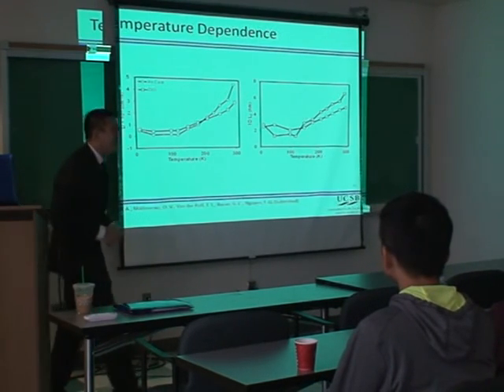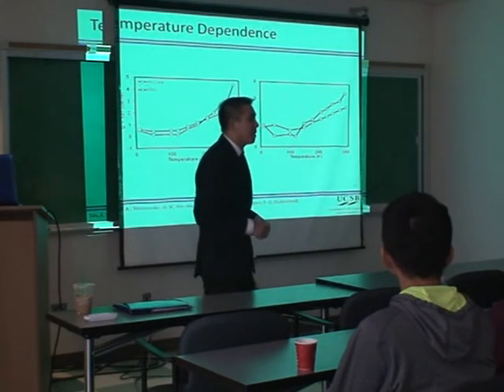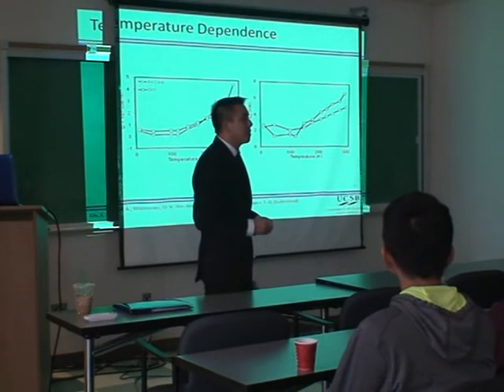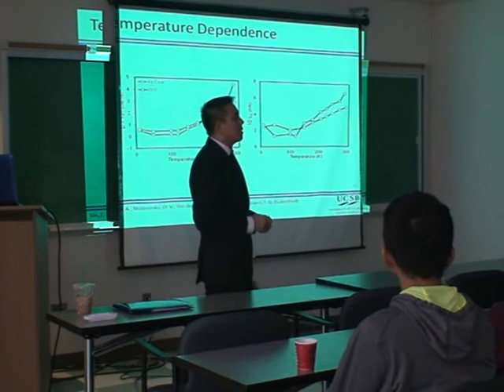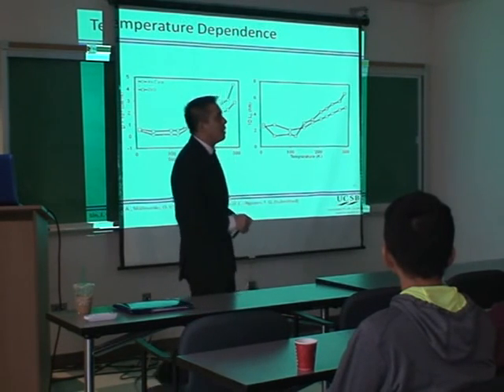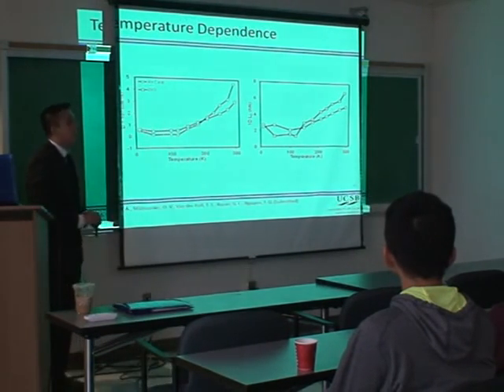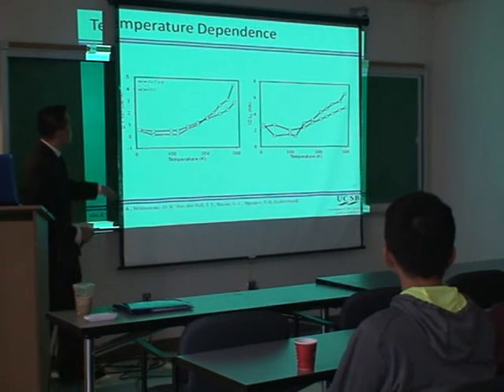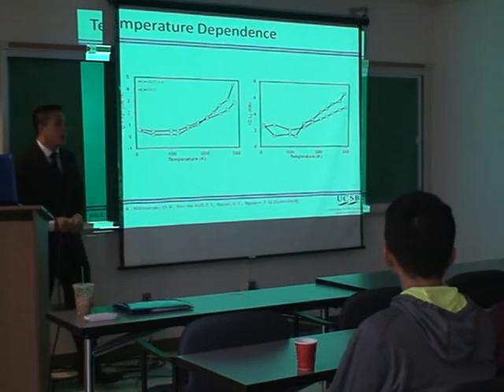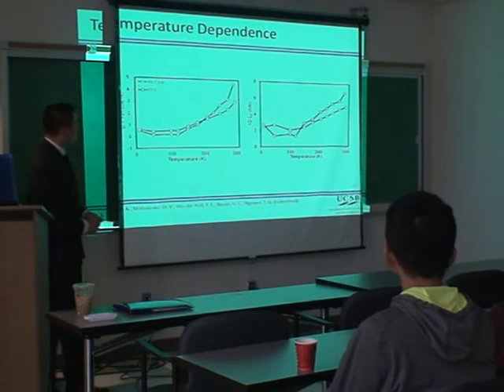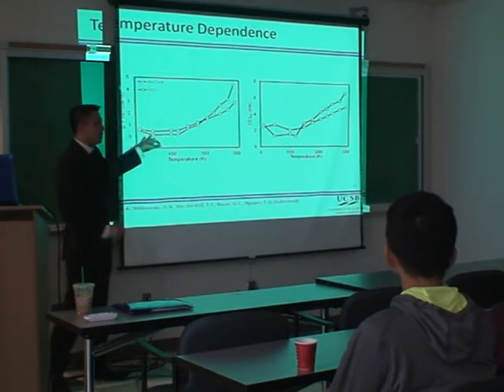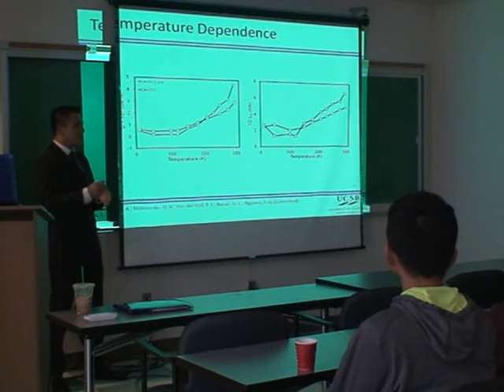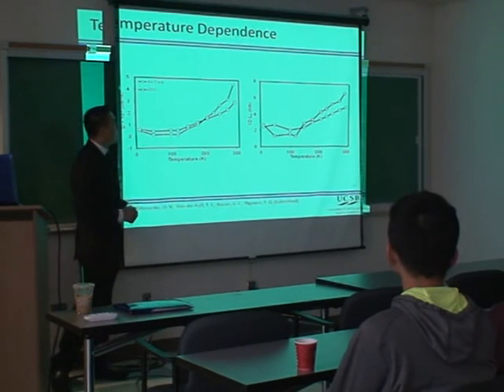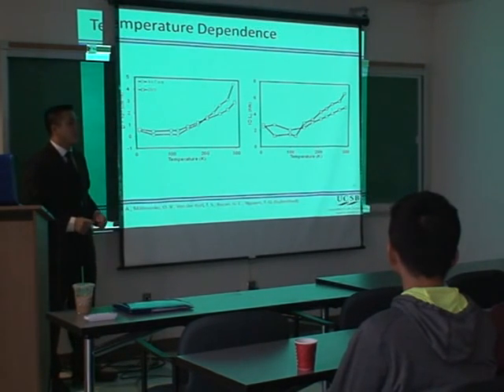Can you rephrase that again? Sorry. Well, do you think that diffusion at low temperature can be caused by the Förster energy transfer mechanism? Yeah, that's definitely a possibility too. And that would be something that we would want to tease out: what is the actual mechanism of this diffusion at low temperature? Maybe one way we could approach that is to further modify the processing conditions. Because one thing we do want to see is how the density of states is changing in these films as we process them, and we have to use other techniques to measure that. I think that would be an interesting question too.